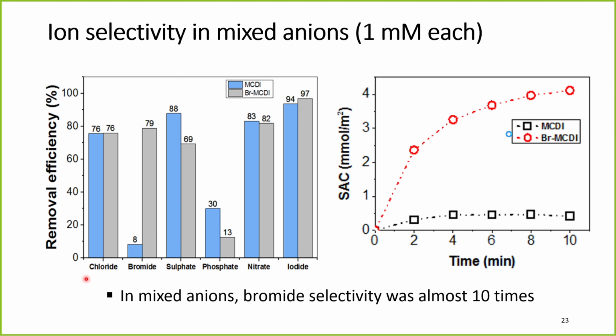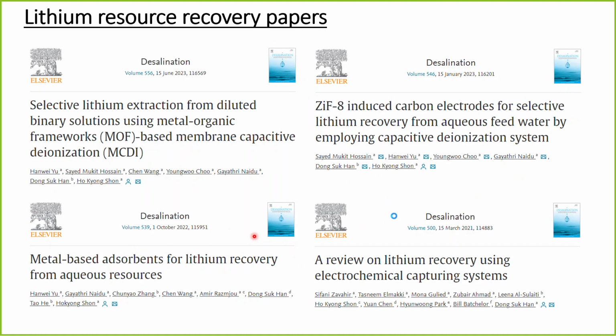We compared different ions: chloride, bromide, sulfate, nitrate, iodide. Bromide selectivity was almost 10 times higher compared to the normal MCDI. So that's what we have developed for bromine recovery, and we are trying to do more real water sample tests. And the next challenge is lithium.